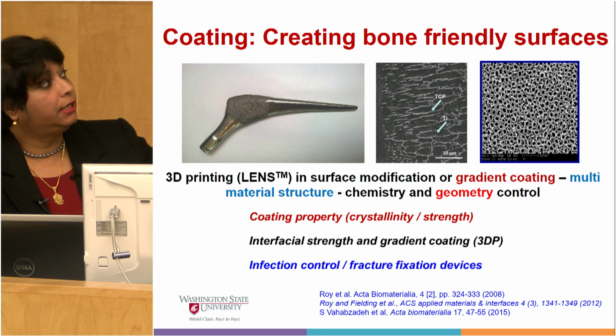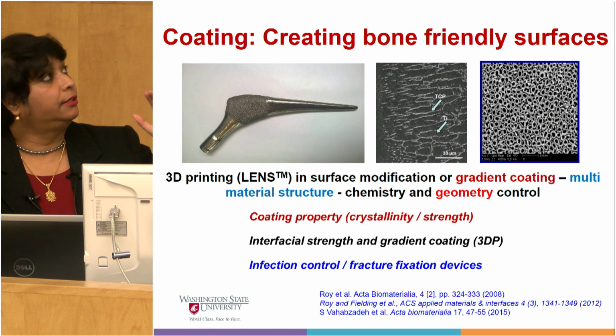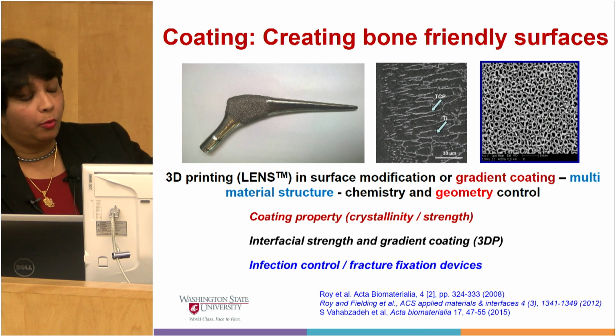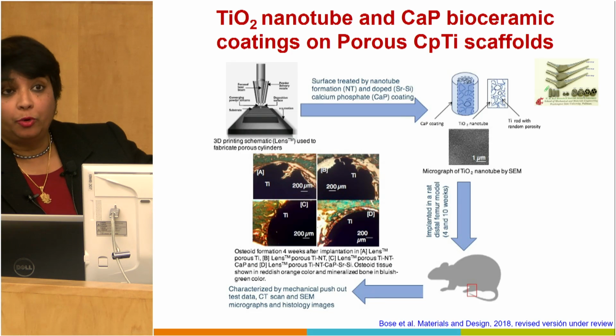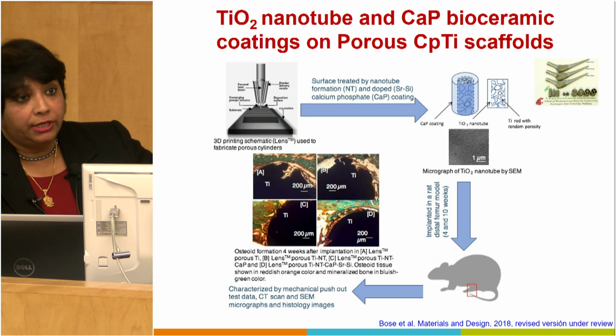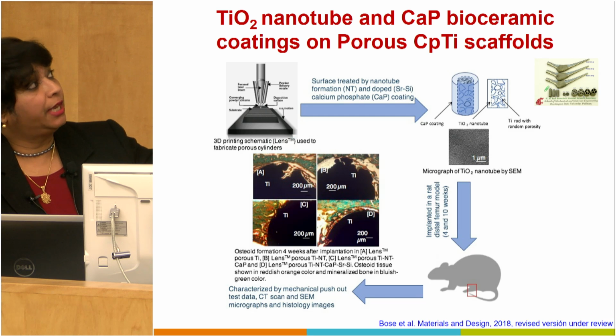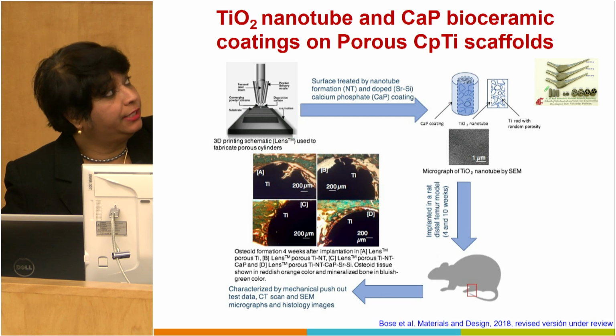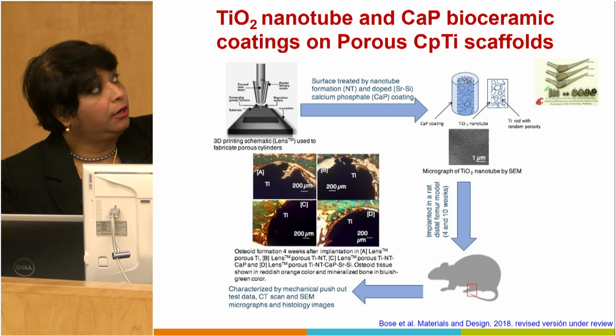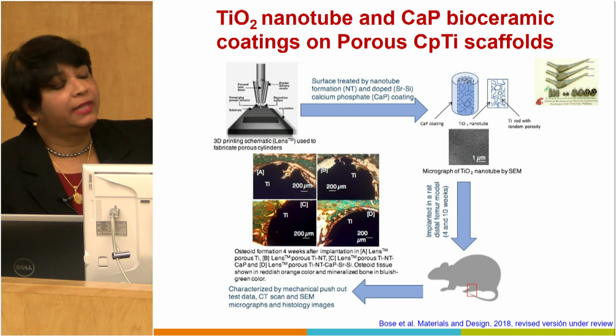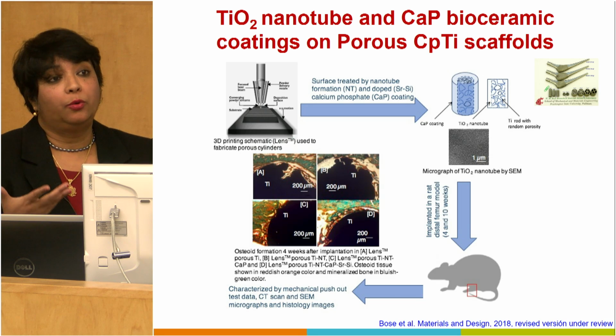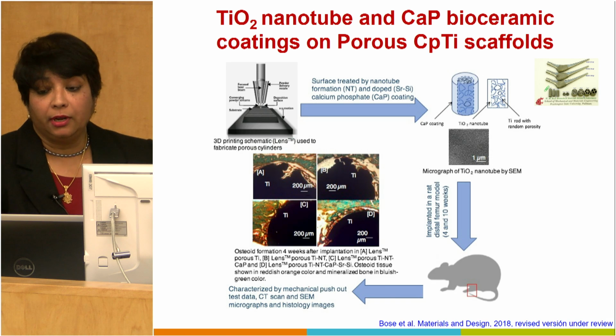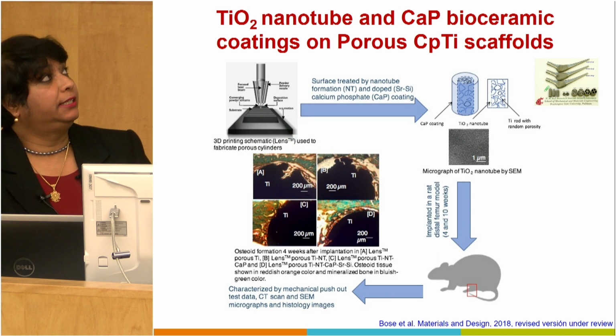This work was actually done by Dishari, who is here. This is part of work where we made the porous metal implant, we coated it, did the surface nanoscale modification, then we coated the chemistry modified calcium phosphate on top of it. In the block of 4 images in the rat distal femur model, the green one that you are seeing is basically bone grown with the chemistry modified surface within the coated implant. So this paper should be accepted anytime.